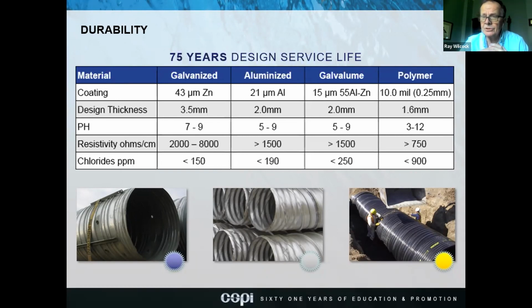The pH levels where it performs, the resistivity, as you can see when you get into polymer laminated, it performs in almost pretty well any environment. And then the chlorides, which are mainly salts. In that particular area, mostly salts. There are others for agricultural runoff and so forth, but it is mainly road salt that we're concerned about.